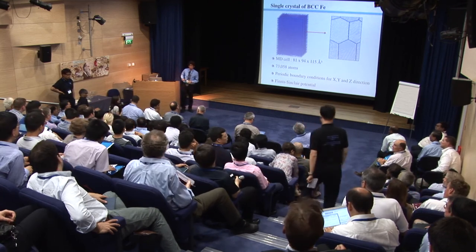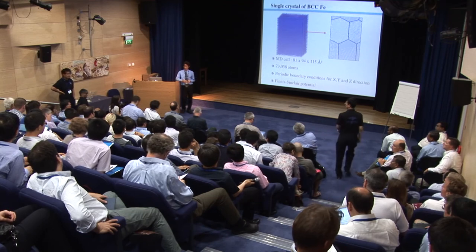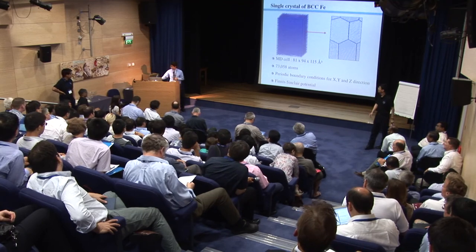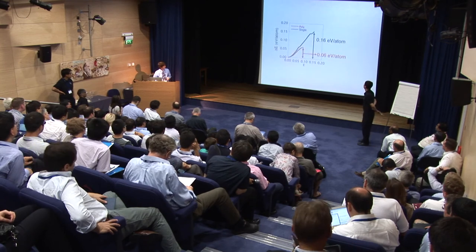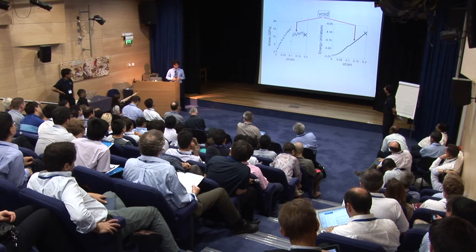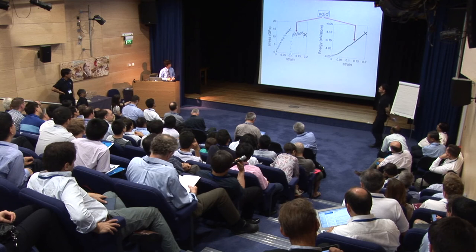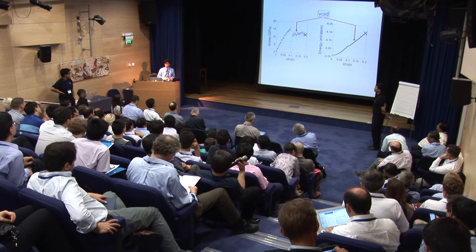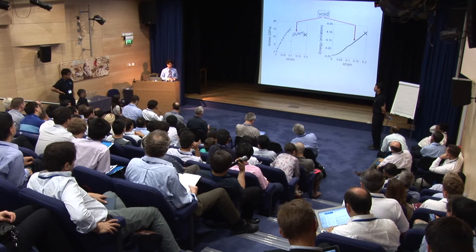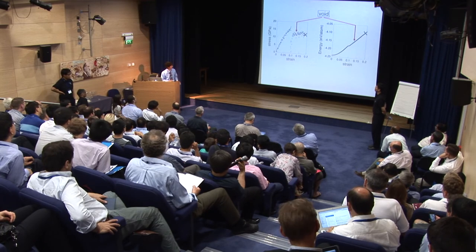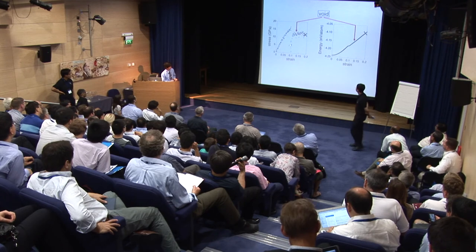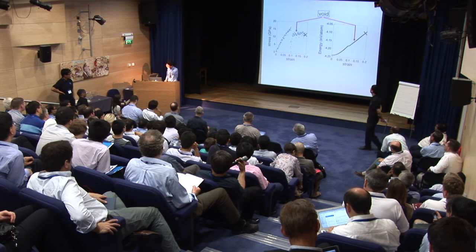Thanks. That was very interesting and different. I have a question about the stress strain curve that you showed. I think it was a single crystal. Yes, single crystal. I'm not sure I understand why there's such a discontinuity at 10% strain, because it looks like the kind of shape you might get at yielding due to the Cottrell atmospheres and the carbon and the dislocations. But obviously here you don't have any carbon, so I wondered what was the reason for that shape. You mean this part? Yes, it peaks and then drops down again. I'm not sure if that's an artifact or if there's a physical explanation.